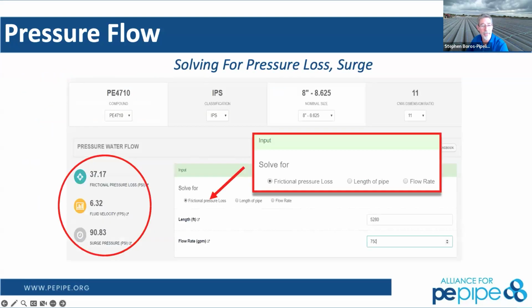So when you go in and solve that, you can solve for it in different ways. Do I want frictional pressure loss? Do I want to calculate what length of pipe I need to get a certain pressure loss, or my overall flow rate? For this situation, we want to look at my frictional loss. So over a mile of 8-inch DR11 pipe, you look over on the left-hand side for your results. My frictional pressure loss over that mile is 37 psi. You're going, wow, that's really high. But this is a mile, and you're operating at over 6 feet per second flow velocity. So you have a fluid that's moving pretty quick through there.